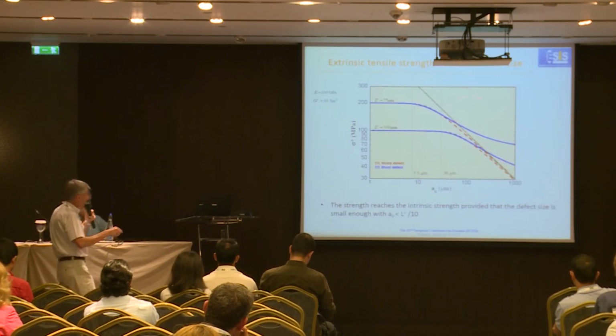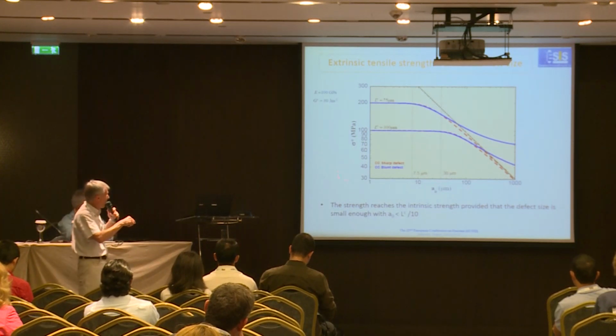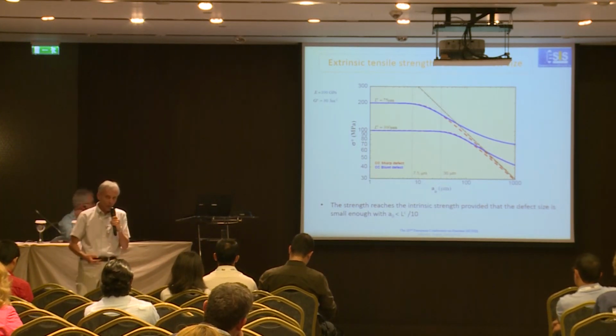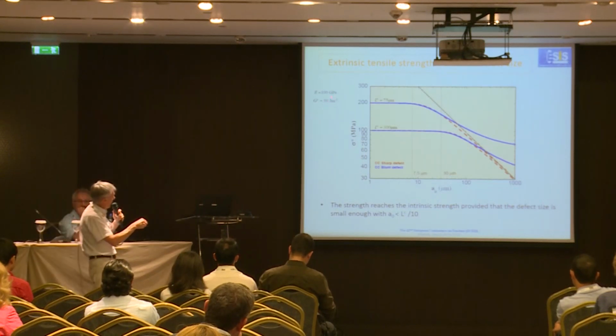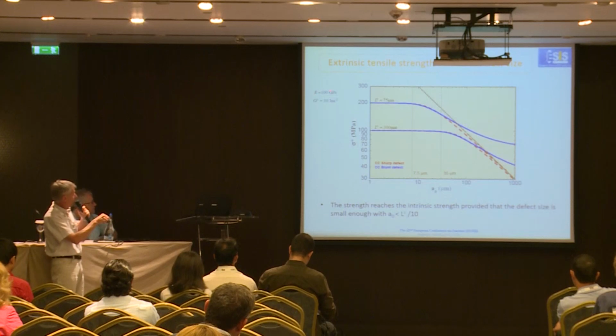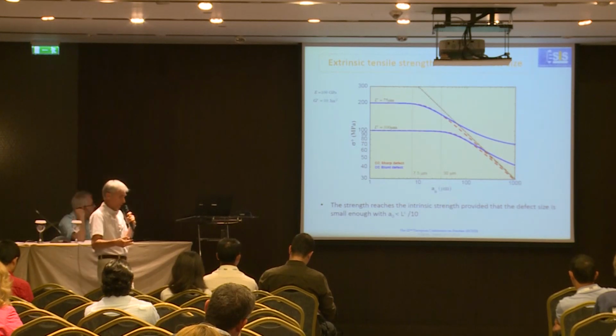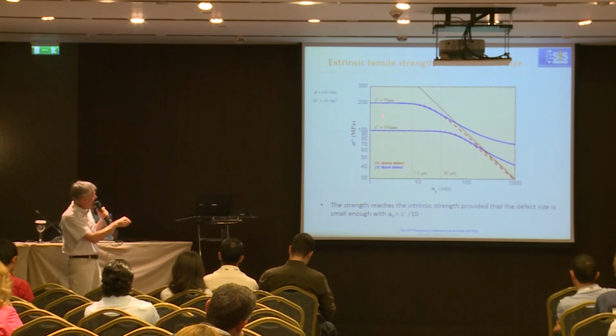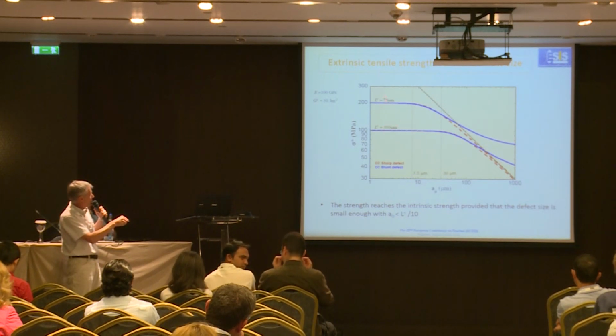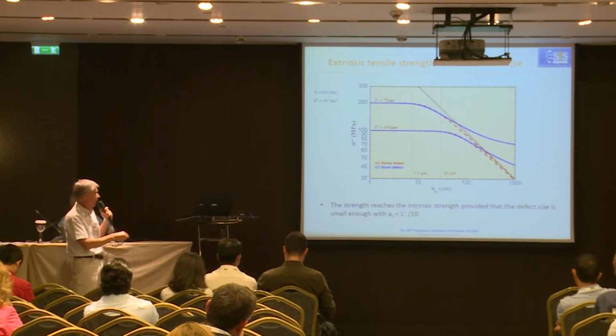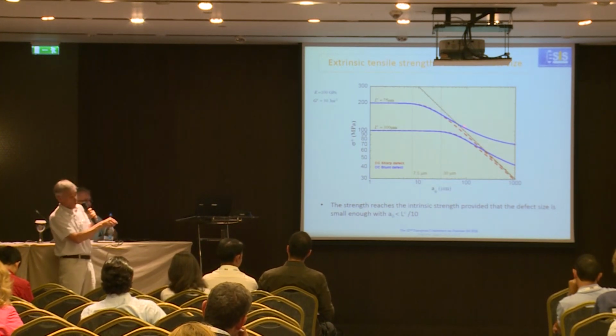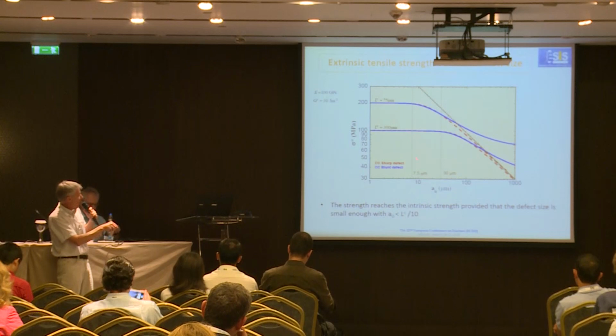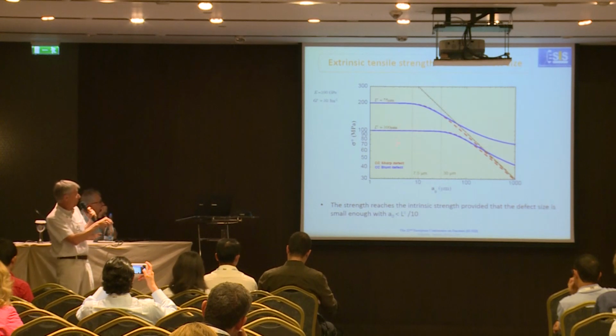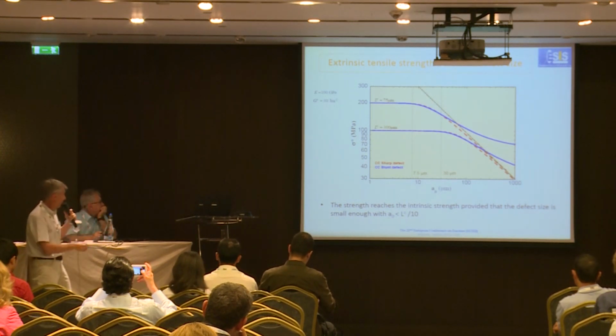Well, we can plot this in this graph without any non-dimensional numbers, just to explain one more time. I select two materials with the same fracture energy, but I change the intrinsic strength of the materials, which changes the characteristic length to 300 and 75 microns. And you can see that you observe, of course, the same effect. You have a plateau, and if the defect is small enough, you can ignore the presence of the defect. In fact, you reach the intrinsic tensile strength.